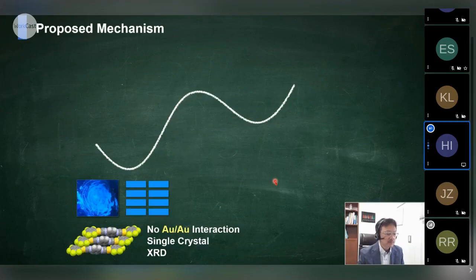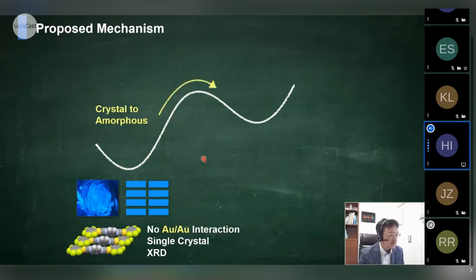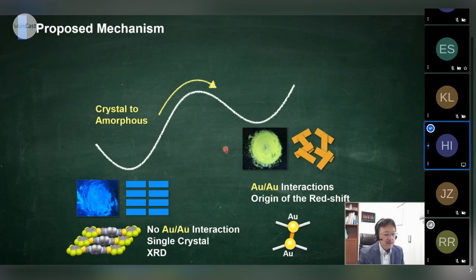This page may show you a cartoon-like explanation of the mechanism of the color change phenomena I showed in the first movie. In the first state, the blue color state, the compound is in a crystalline state. We already checked the crystal structure of this state, and the addition of mechanical stress can change this crystal structure to amorphous. And in the amorphous state, we believe that aurophilic interaction, which is an attractive interaction, can change the luminescence color of gold complexes. Maybe in the amorphous state, this aurophilic interaction can form.